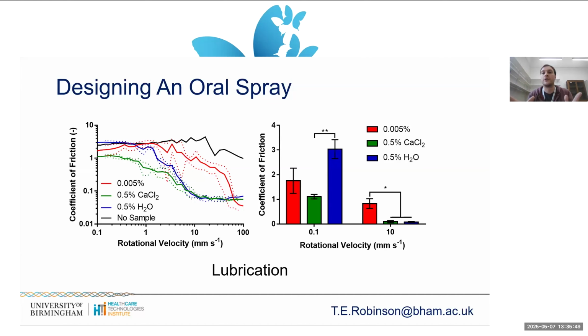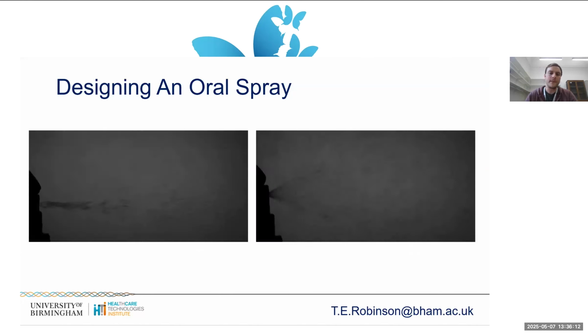these materials so good. So retention on the inside of the mouth, how long it stays there: if you take all the polysaccharide out of it, it'll act like water and it'll only stay there for a couple of seconds maximum. Whereas if we try and create structured gel materials from the polysaccharides, then we can start to increase the material properties, get lubrication, and get all that stuff we want. So you can see that this is quite a marked effect on the spraying. We go from that jetting behavior to really good spraying behavior.